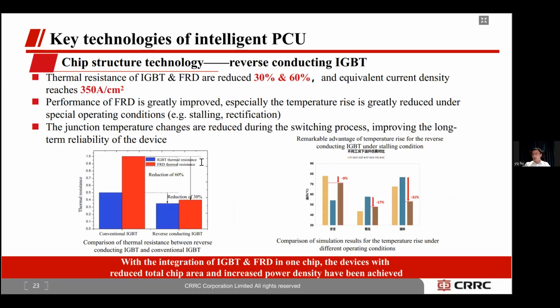By integrating IGBT and FRD on one chip, a reverse conducting IGBT device with reduced chip area and improved power density is realized. When using the reverse conducting IGBT devices, the thermal resistance of the IGBT and FRD is reduced by 30% and 60% respectively, and the equivalent current density reaches 350 amperes per square centimeter. The performance of the FRD has been greatly improved, especially in special conditions. Temperature rise is greatly reduced. The change of junction temperature in the switching process is reduced, and the long-term reliability of the device is improved.